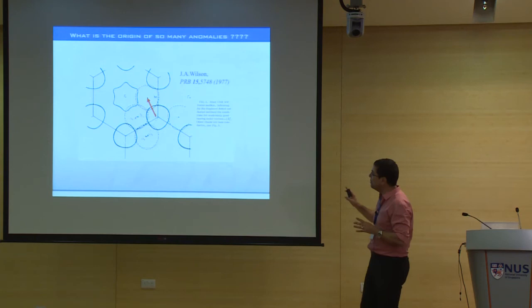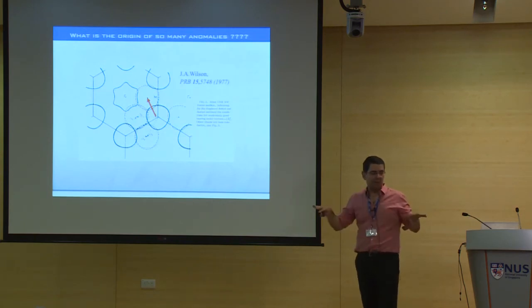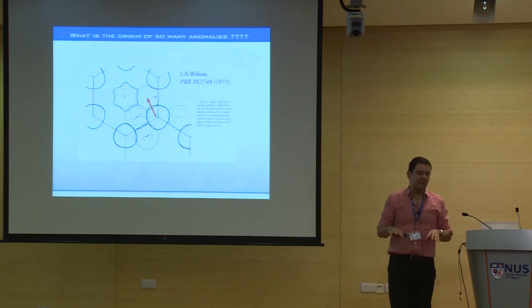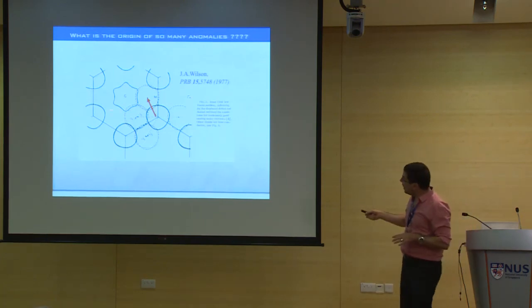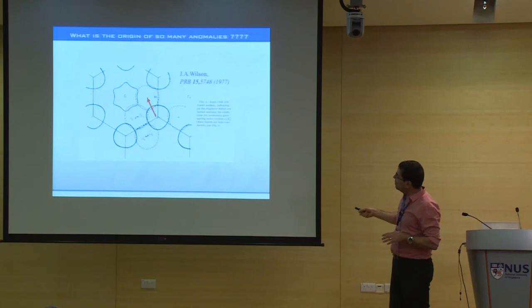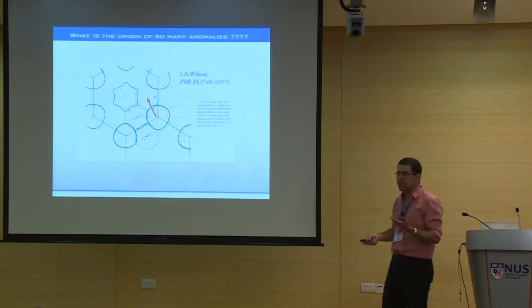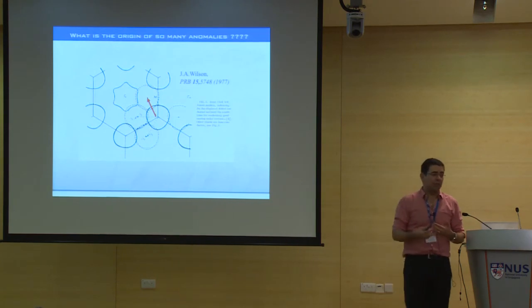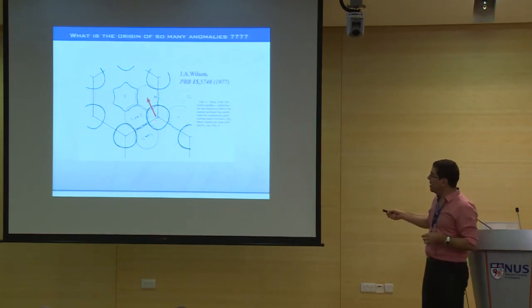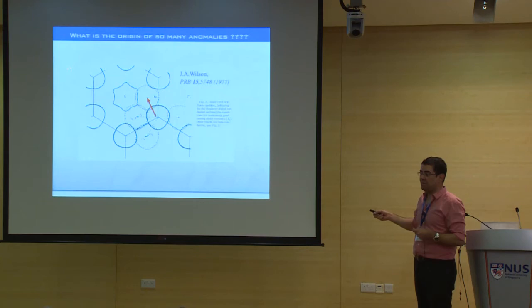Okay, so actually, many people then started to look at the Fermi surface, and this is, again, an old paper, but I think it's very representative. So you see, this is how the Fermi surface looks like. The band structure looks like at the Fermi level. So you have an internal Fermi sheet here, so this is a Fermi surface, and you have another one at the edge. So actually, at this time, it was theorized that the charge density wave was actually triggered by the nesting between these bands. Okay?